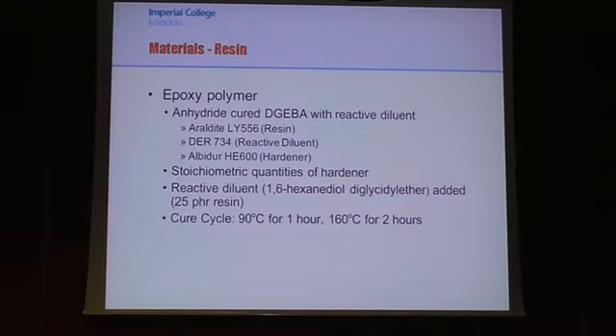So the reactive diluent used was DER 734 from Dow. It was basically we replaced 1/4 of the resin with this reactive diluent, and we used anhydride hardener HE600 from Evonik. Material cycle was 90 degrees 1 hour, and then 160 degrees for 2 hours. TG of these systems is about 130 degrees.